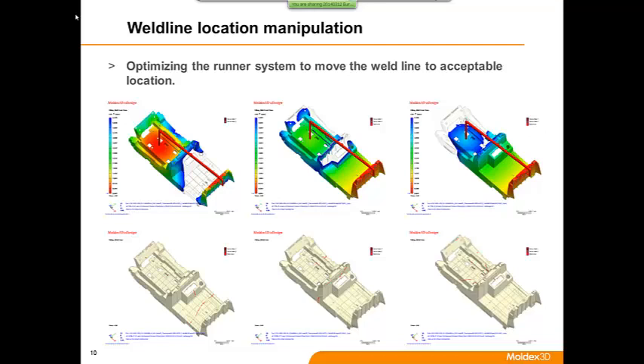So the first thing, of course, is to accurately predict the weld line location. So you can see from this graph, after you manipulate different gate locations, from the bottom 3 charts, you can see originally it's a really large red line across the bottom side of this part. And after you manipulate the gate location, you can see we scatter the weld line location around. The weld line is inevitable because you have 2 gates and it's not a hot runner system. But right now you can see it's not a straight long line, it's not continuous, so it's doing less damage to the part if you have a structural problem.